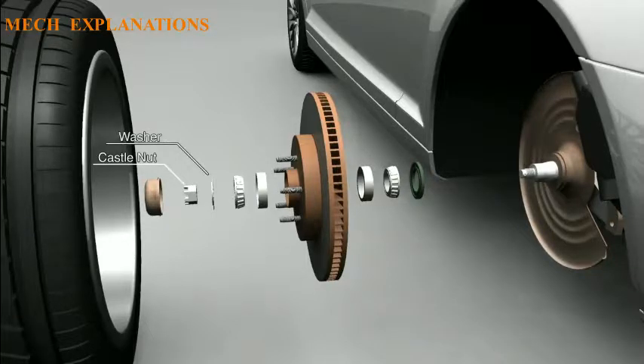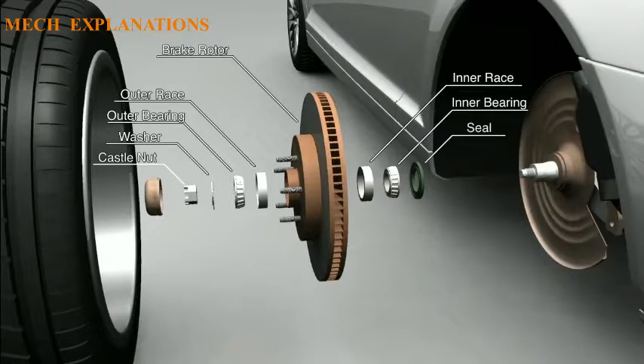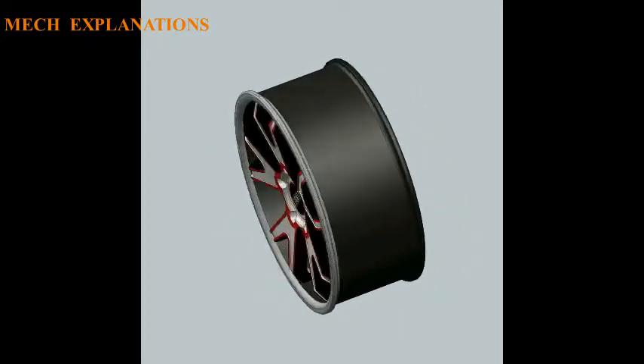Until this time, most aluminum wheels suffered from low ductility, usually ranging from 2 to 3% elongation. Because light alloy wheels at the time were often made of magnesium, often referred to as mags, these early wheel failures were later attributed to magnesium's low ductility, when in many instances these wheels were poorly cast aluminum alloy wheels. Once these aluminum casting improvements were more widely adopted, the aluminum wheel took the place of magnesium as low-cost, high-performance wheels for motorsports.